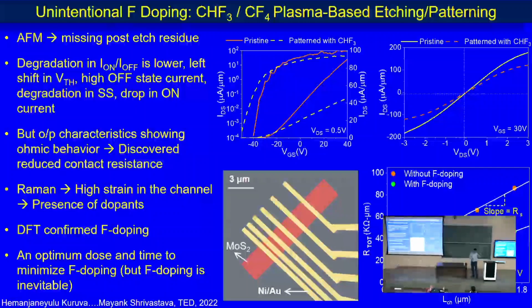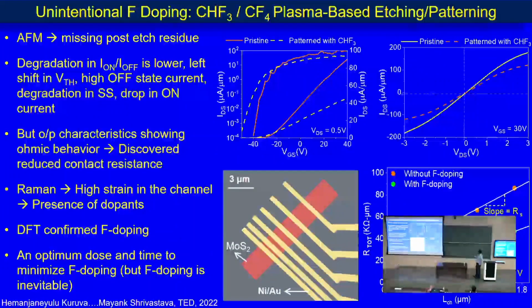So of course that was also a discovery. While we were trying to solve the etching problem, it was also a discovery that fluorine can also dope the contact, and we found that with and without fluorine there is almost an 8 times difference in the contact resistance. But of course, as a function of that optimization, we also fixed a problem. Fluorine was also sitting in the channel, which was introducing a tensile strain across the channel, affecting the mobility, which was causing a drop in the current. So we fixed that problem. We boosted the drive current, and also found a way to further engineer the contacts with fluorine.